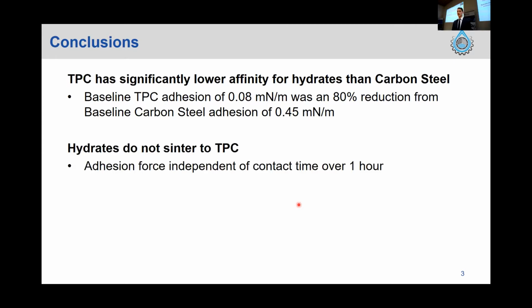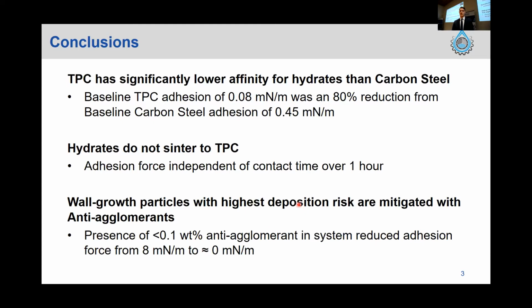The next was that hydrate particles did not sinter to the TPC material. This is specifically about hydrate particles that had formed in the bulk fluid sintering to the material. This was proven by the adhesion force being shown to be independent of contact time, tested up to 1 hour. And the last conclusion was that wall growth particles tested in this research showed the highest deposition risk, and I'll talk about those a bit later.